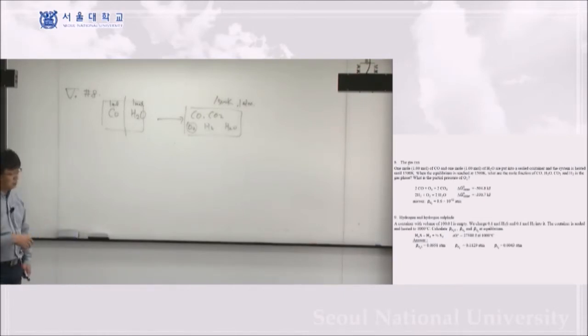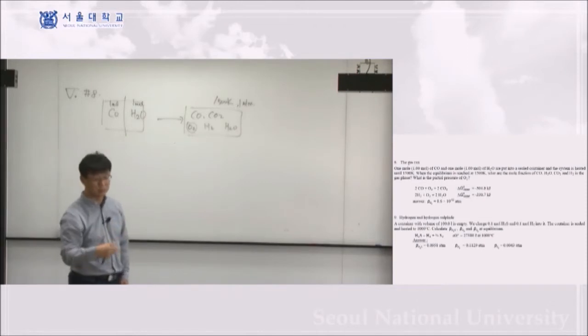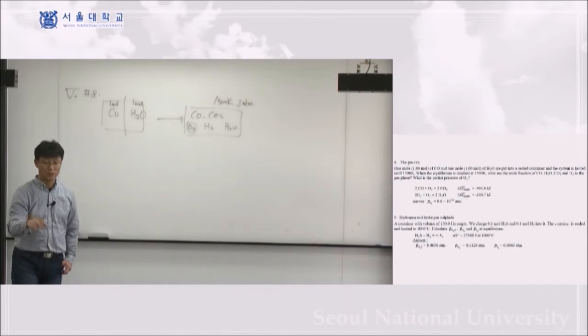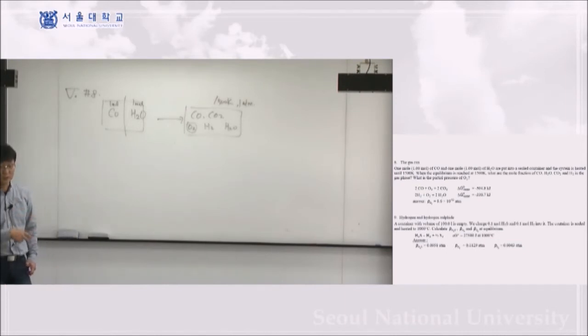So in this case, we don't care about how this is moving, but we want to know what the final state itself is. And the only reason we give the 1 mole of CO and the 1 mole of H2O in the beginning is that we want to make a mass balance. Because at least we have to know the carbon amount, the oxygen amount, and the hydrogen amount in the final state here. We cannot generate additional mass during the chemical reaction. So that's the only reason we give the initial state.